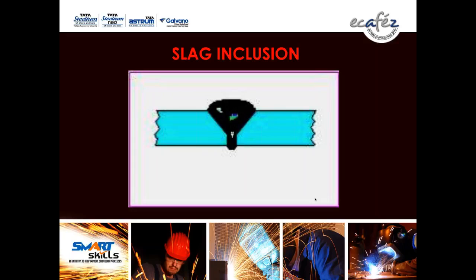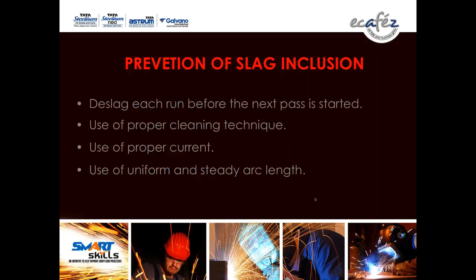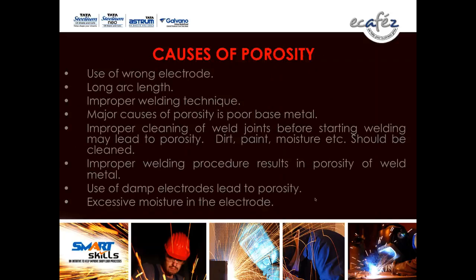This is a picture of slag inclusion. Prevention of slag inclusion: deslag each run before the next pass is started. Use proper cleaning technique, proper current, and uniform and steady arc length for the prevention of slag inclusion. Causes of porosity: use of wrong electrode, long arc length, improper welding technique.